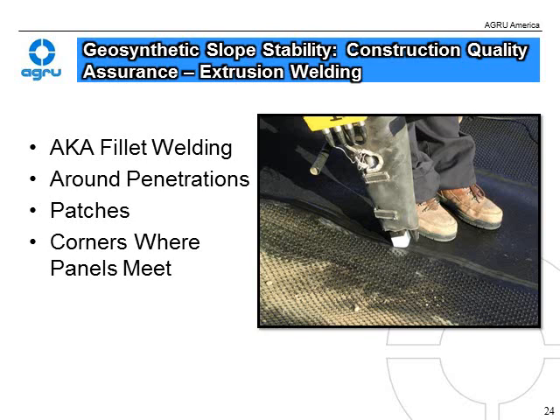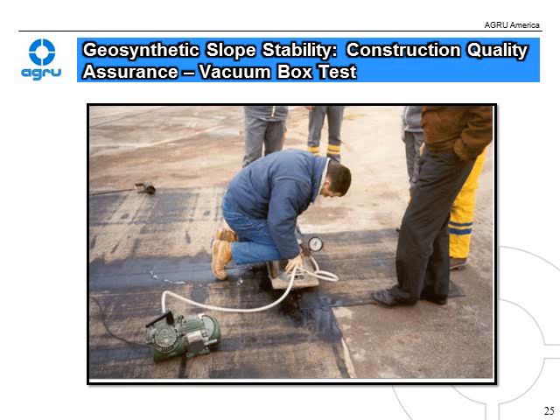The other welding technique is extrusion welding, otherwise known as fillet welding. You'll find this done around penetrations, for patches where destructive samples are taken from the double wedge welds, and then corners where panels meet. Now here's an example of a construction quality assurance test on an extrusion weld or a fillet weld. It's a vacuum box. It simply applies a soapy solution over the seam, as you see here, and then applies a vacuum and watches for soap bubbles bubbling up around the weld. And of course, this test method needs 4 to 5 supervisors all standing around watching it done.